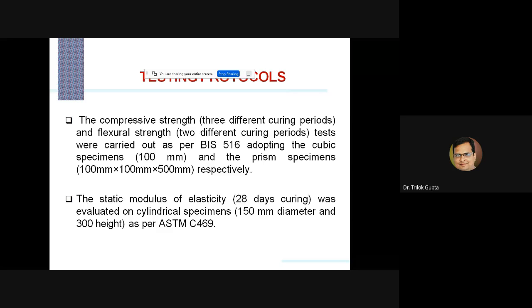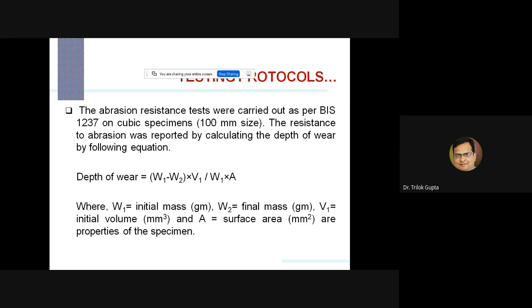Compressive strength was performed on 100 mm cubes, and flexural strength on beam specimens of size 100 mm by 100 mm by 500 mm. The curing periods for flexural strength were only two, 7 days and 28 days. For compressive strength, we calculated it for three different curing periods: 7 days, 28 days, and 90 days. Static modulus of elasticity was calculated only for one curing period, 28 days. It was determined on cylindrical specimens having a diameter of 150 mm and a height of 300 mm, and the code followed for the static modulus was ASTM C469. Three specimens were tested for each type of test.